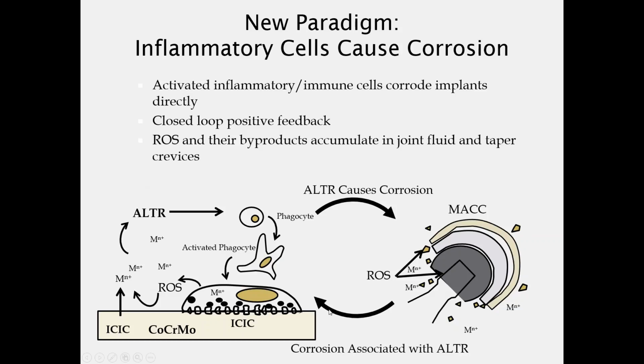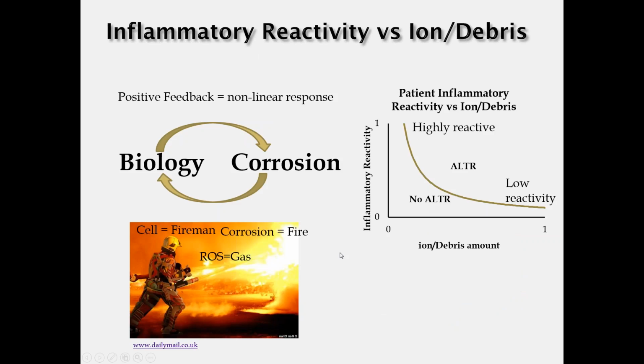We could have debris from the device inducing the cells and setting this up, and in fact the phagocytes can get into and alter and influence the taper junctions, the bearing surfaces, which then may modify the mechanically assisted corrosion processes. And so essentially what I want you to remember is it is no longer a one-way arrow of implant debris and corrosion causes biology, but that biology can also influence and affect corrosion on the device.